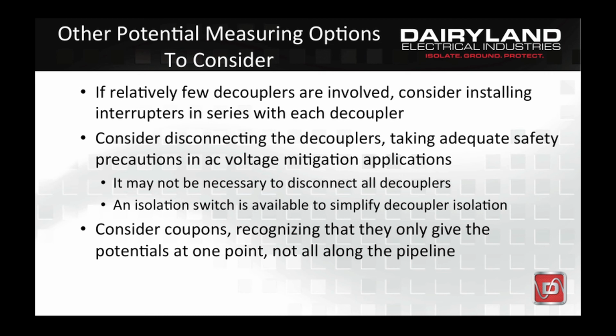Based on field testing done by Dairyland, it is not necessary to disconnect all decouplers on some pipelines in order to obtain an accurate potential measurement, though an increased measuring delay time will likely be required. By leaving some decouplers installed with sufficient spacing between them, the voltage may be kept to safe levels with accurate off potential measurements still possible. Due to the many variables involved, it is not presently possible to provide definitive guidelines as to the minimum decoupler spacing along a pipeline that may enable accurate off potential measurements.